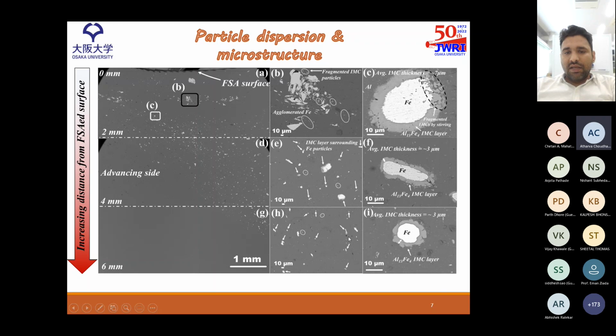Now the interesting thing is that the particles in the top region don't have a well-defined shell intermetallic layer, as can be seen here. This is only for very few particles we have observed. However, it is around 7 micrometer thick, whereas in the middle and the bottom, most of the particles have an IMC layer around them. However, the thickness is around 3 micron in the middle and the bottom section.